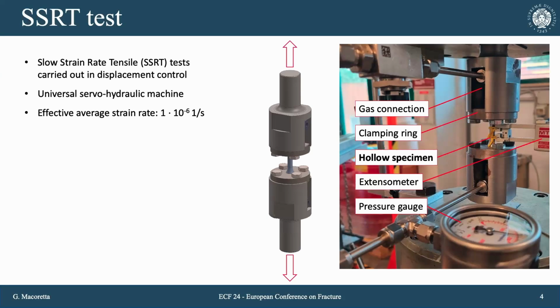Here you can see the test configuration. In the middle of the picture, you can see the hollow specimen with an extensometer to monitor the deformation of the central portion of the specimen. You can see the clamping ring, which is simply a fixture that applies the load to the specimen, decoupling the load from the pressure fixture. We have the gas connection, and on the gas connection, a pressure gauge to monitor the effective pressure in the specimen during the test.